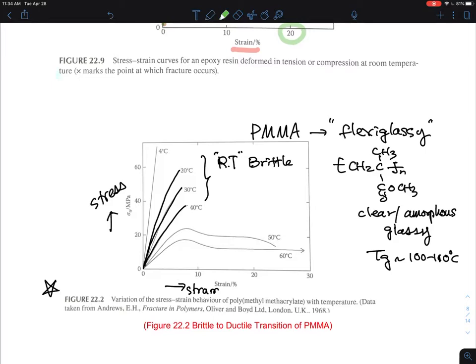But now, when you increase a temperature to something like 50 degrees C, you start to see the yield behavior. And this one goes on. And if you do the 60 degrees C, that's even higher temperature. So this is an indication of temperature higher than 50 degrees C for PMMA. And that's ductile. So what do you see? We are seeing the brittle to ductile transition simply by changing the temperature from 40 to 50. And so brittle to ductile transition of PMMA. This is one of the iconic experiments that has been well studied. And many people understand this.